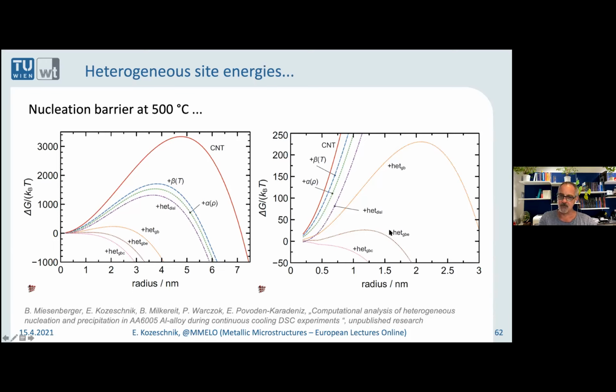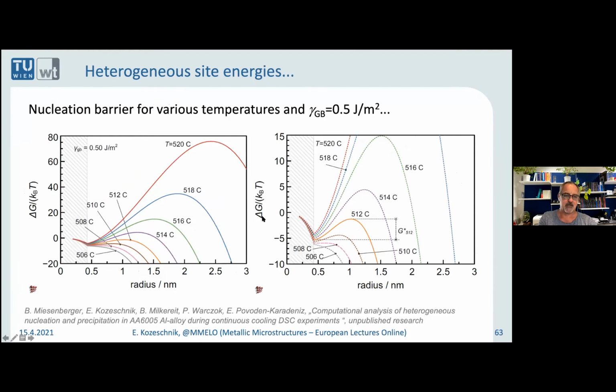And this is a close-up, and the next diagram shows an even higher close-up. The variation in the barrier is now only in the temperature, and it's only for the barrier at grain boundary corners. There you can see that with decreasing temperature, grain boundary corner energy will become negative.